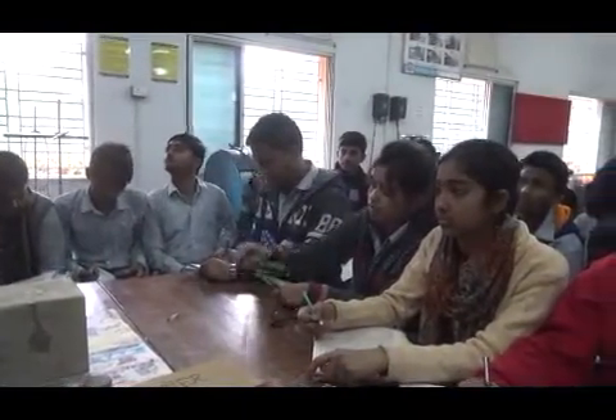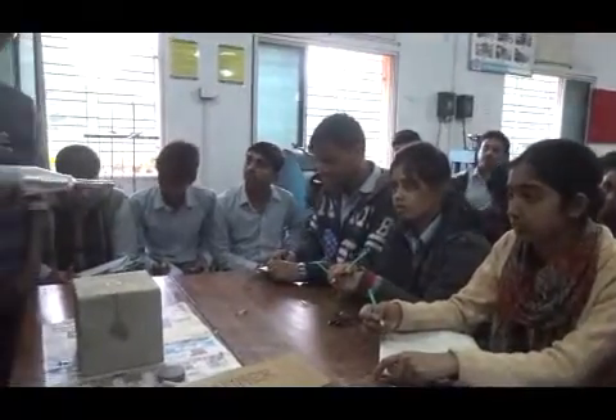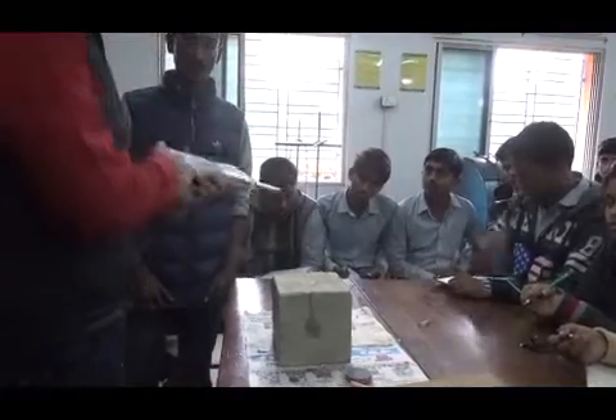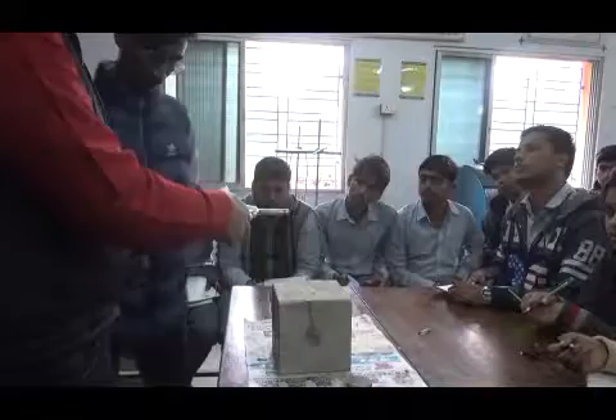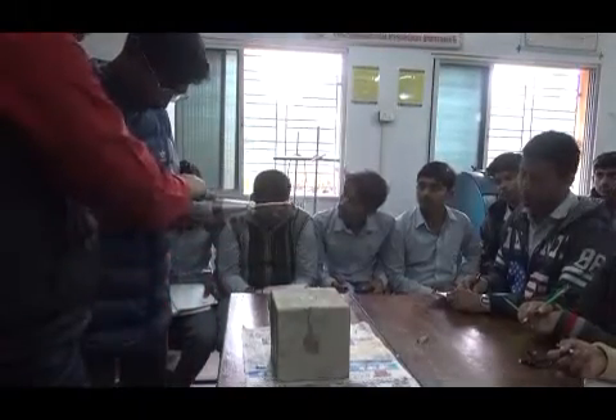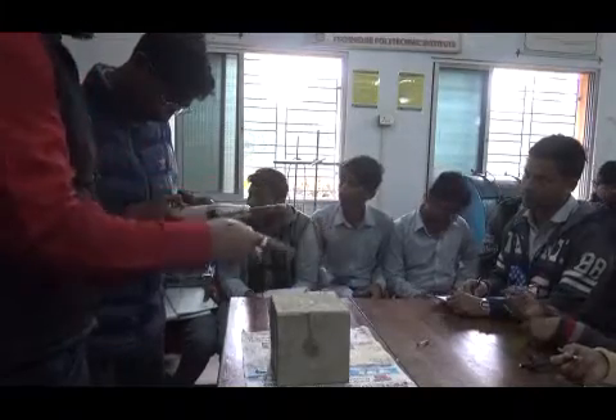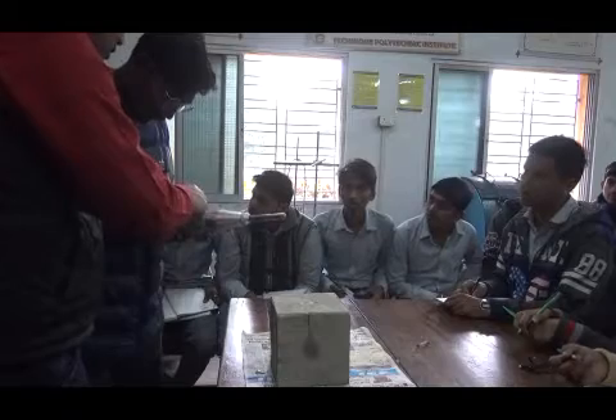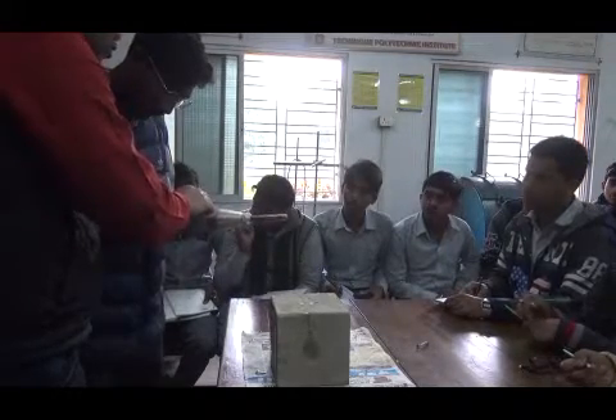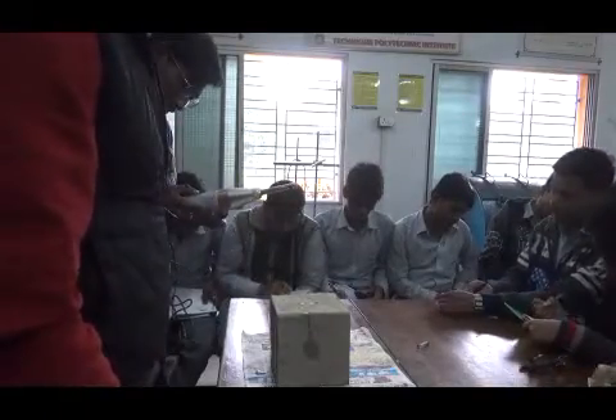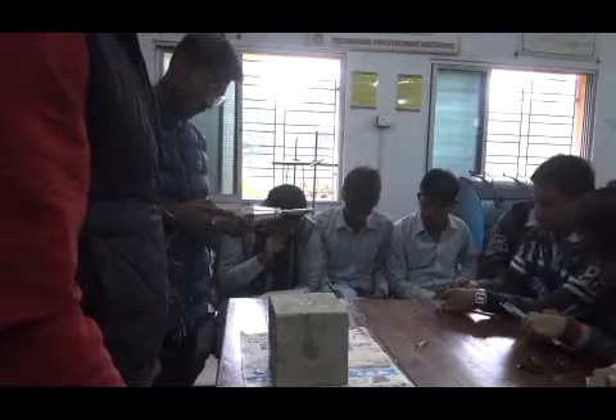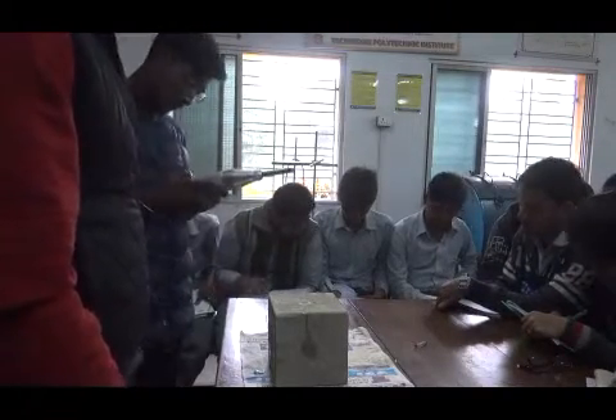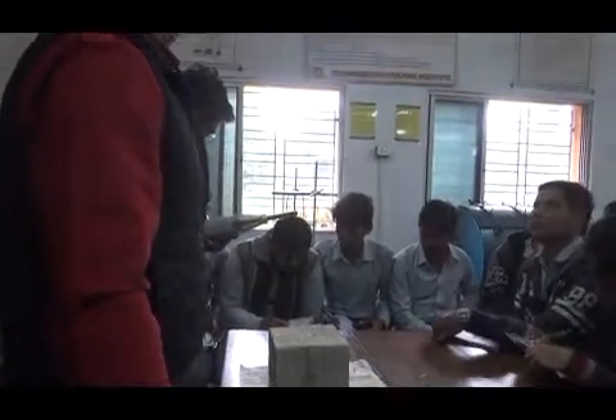So by this method we can determine the compressive strength from the graphical representation and easily determine the grade of concrete. What is the compressive strength for the rebound number of 28 which we have got? Here is the value of 28 at an angle of 90 degree and our compressive strength comes as 280 kg per centimeter square. From that we can conclude that the grade of concrete is approximately M25.